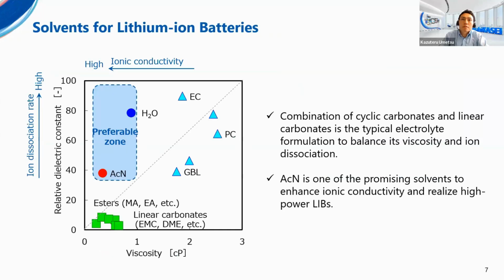This graph shows the viscosity and relative dielectric constant of the solvents used in lithium-ion batteries, which affect the ionic conductivity. In order to increase the ionic conductivity of the electrolytes, it is necessary to decrease the viscosity of the solvents and increase the ionic dissociation. In other words, the upper left area of the graph is expected to show high input-output characteristics as an electrolyte for lithium batteries. From this perspective, H2O is an ideal solvent. However, its narrow potential window makes it difficult to use as a solvent for lithium-ion batteries.